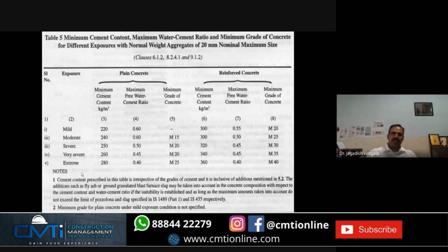That means for foundation, you have to design a concrete of a minimum grade M25, and for the rest of the elements you can go for M20 or above. It depends again on the loads and other things. So anytime when you design a concrete mix, you design the mix based on the exposure condition. And IS permits the maximum cement to use in concrete per cubic meter of concrete, it is 450 kg.